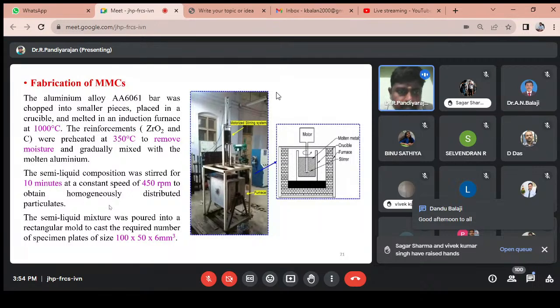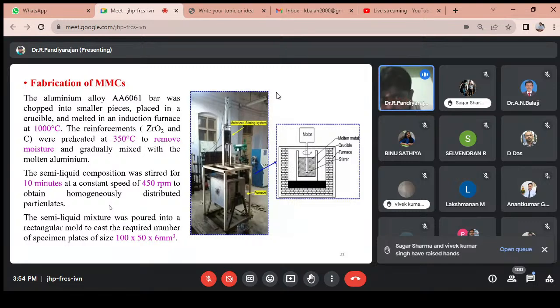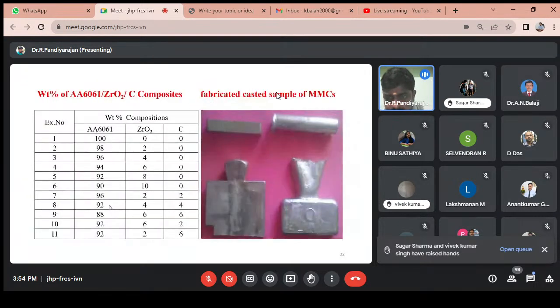If you do not preheat the reinforcement particulate, many defects are produced in the metal matrix composite material. So definitely you have to preheat the reinforcement particulate. After that, we mix the matrix material to fabricate a homogeneous distribution of matrix and reinforcement particulate in the aluminum based composite material. This is the example diagram of metal matrix composite material with various dimensions, casted pieces, and different weight percentages of matrix and reinforcement particulate.